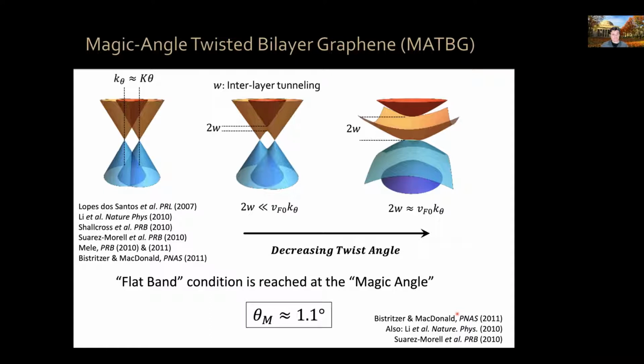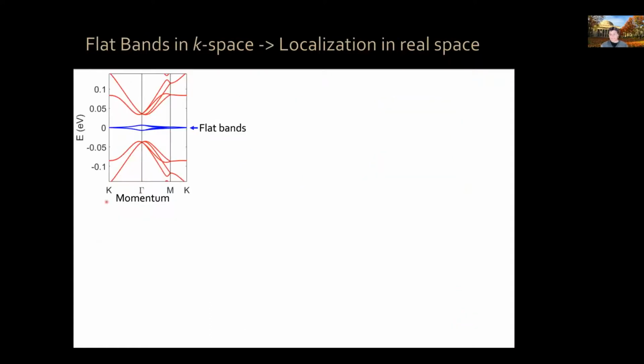Now, before I showed you a cartoon; this is actually a real calculation of the electronic structure for magic angle twisted bilayer graphene. As you can see, there are these flat bands. These are other remote bands, and these flat bands are not perfectly flat, but they're much flatter than the original graphene dispersion. Now, flat bands in momentum space mean that, if you look at the electrons, where are the electrons in real space that are in these flat bands?